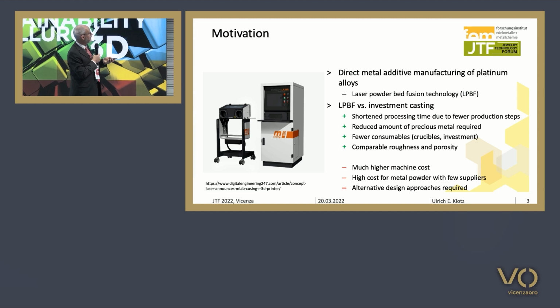I mentioned laser powder bed fusion technology. We've heard about selective laser melting; some people speak of laser beam melting. These are different names for the same technology. The principle is that you apply a powder bed in a machine. The powder bed has a layer thickness of 20 to 50 microns, sometimes higher for steels. This powder bed is melted at some positions with a laser, so the part is melted layer by layer because the platform is lowered each layer.